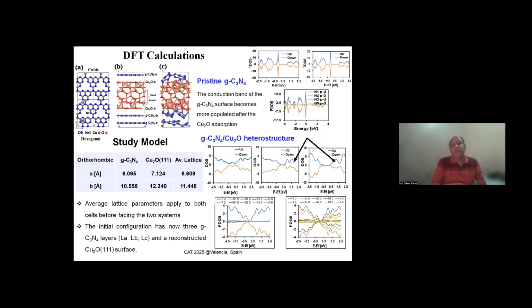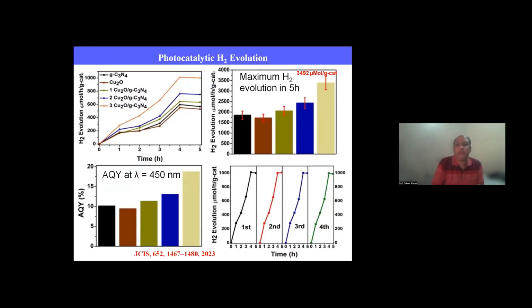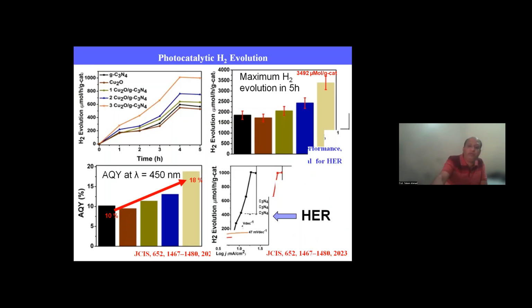During this phase formation, we could see that the conduction band of graphite carbon nitride becomes more populated, which helps explain why the 38% loading of the copper oxide over graphite carbon nitride could give the high amount of hydrogen production, 3.5 millimole per hour per gram of hydrogen with an apparent quantum yield of 18%. In fact, we are the first who have reported this kind of result with the copper oxide nanoparticles.